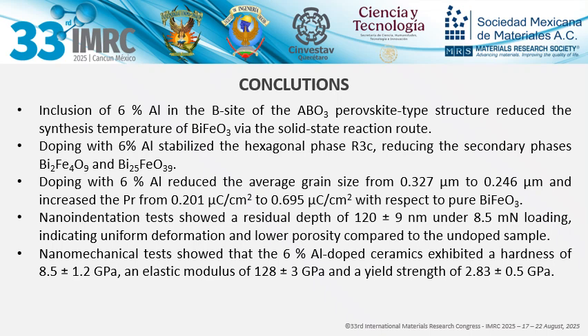Achieved uniform deformation and lower porosity indicated by a residual depth of 120 plus or minus 9 nanometers under an 8.5 millinewton load. Enhanced nanomechanical performance with hardness of 8.5 plus or minus 1.2 gigapascals, elastic modulus of 128 plus or minus 3 gigapascals, and yield strength of 2.83 plus or minus 0.5 gigapascals. These results indicate that aluminum-doped bismuth ferrite has strong potential as a lead-free functional ceramic material, applicable in sensors, actuators, ferroelectric devices, and energy harvesting systems.